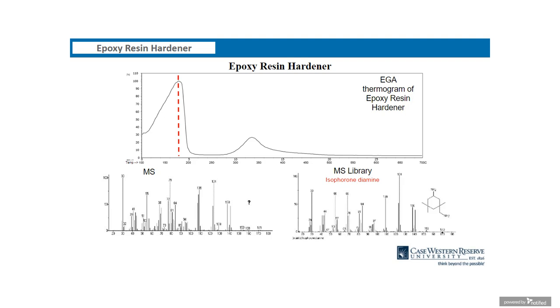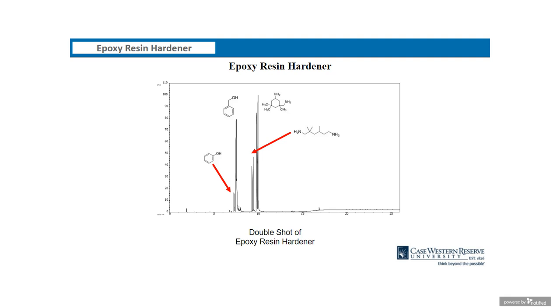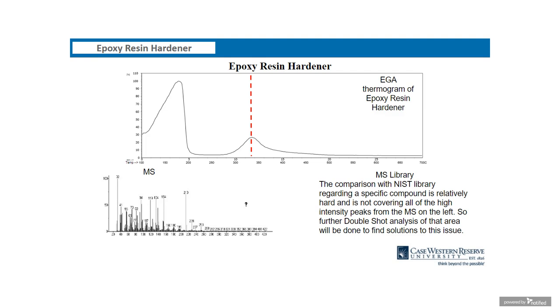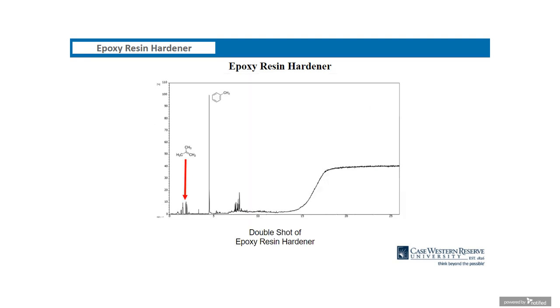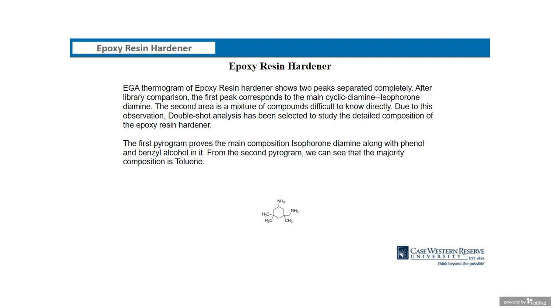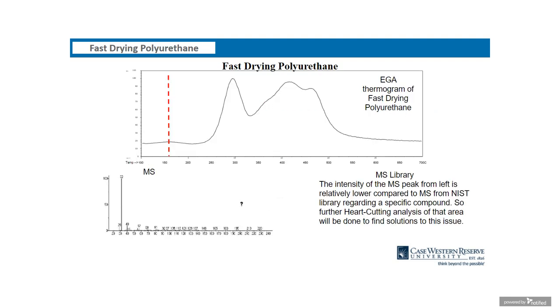And then these two peaks confirmed the presence of two fractions. And we were able to confirm that again by a cut experiment. But again, just to confirm, even from double shot, we can see that it's a mixture of two different types of amine diamine compositions. And again, some of the experiments to confirm the presence of other components on your resin